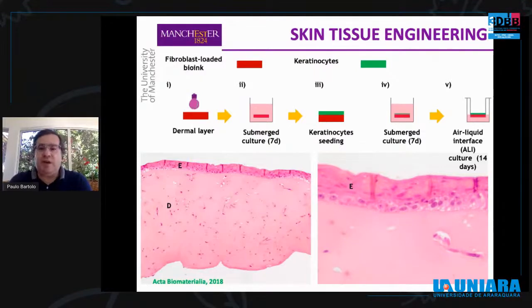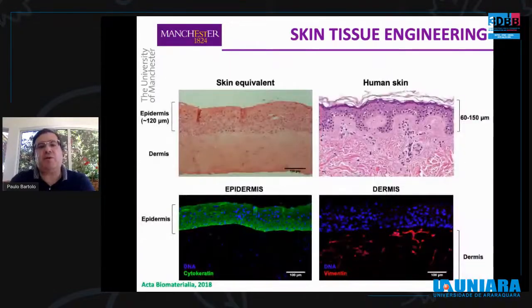And then we print the bio-ink containing keratinocytes, and again submerge the material in culture media during 7 days. And after that, we expose the upper layers to air, creating an air-liquid interface to induce stratification. And we obtain, using this approach, an artificial skin with high similarities with the human skin, not only in terms of its organization, in terms of the shape and organization of the cells in the different layers, thickness of the layers. We are currently increasing the complexity of our approach, adding other types of cells.